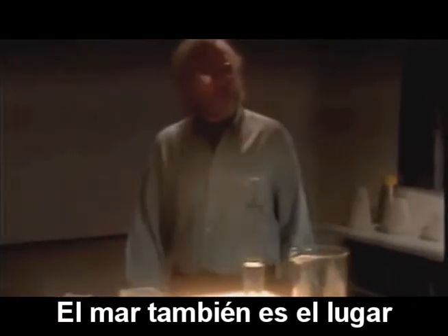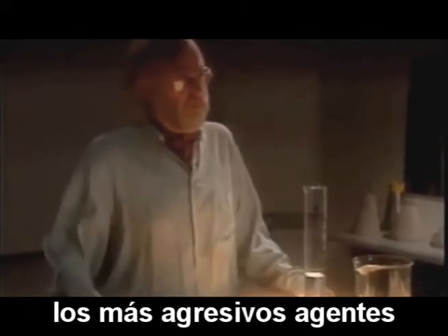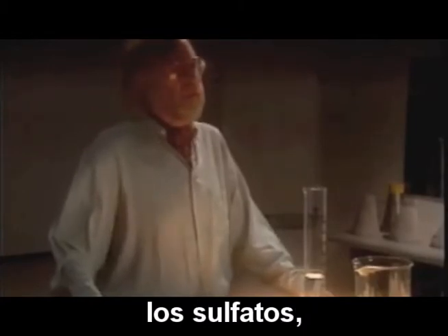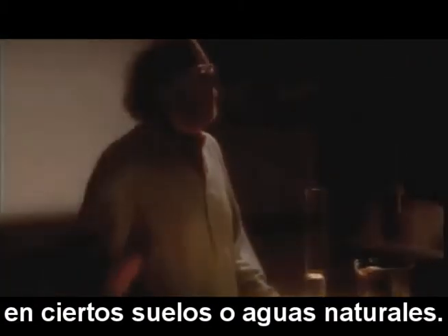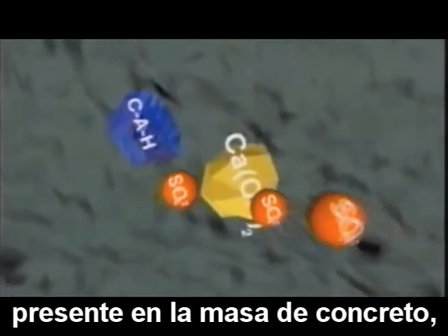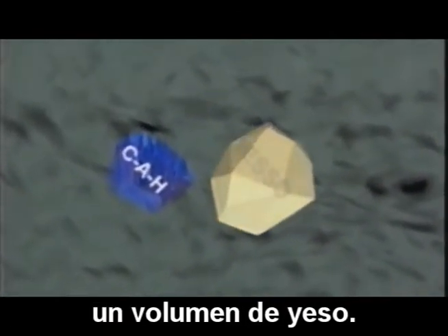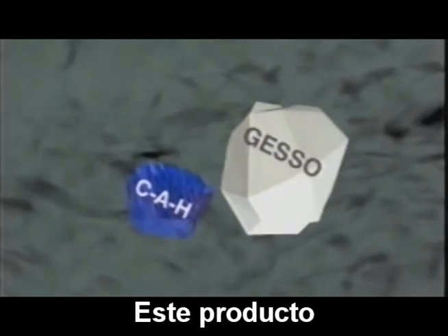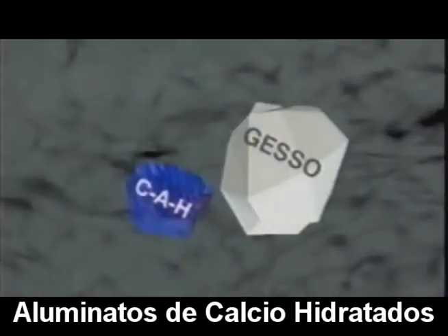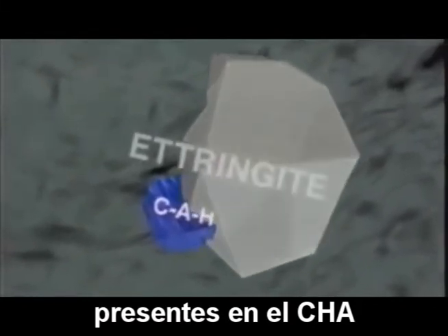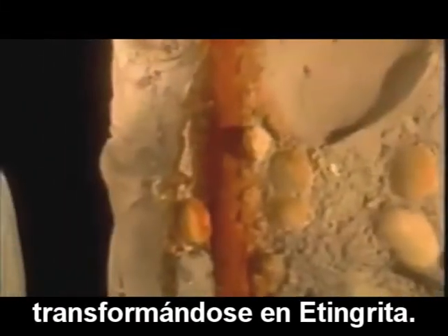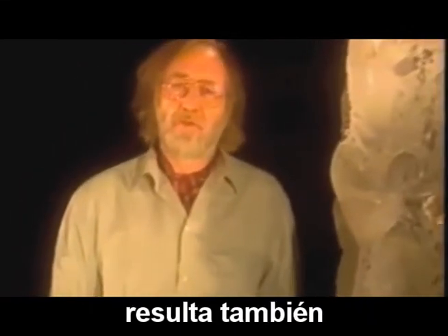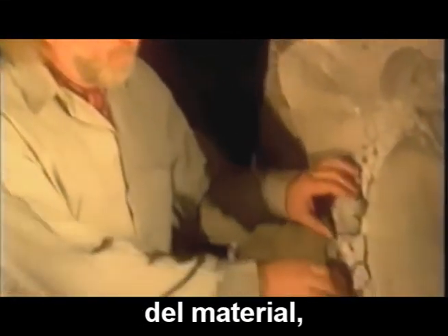The sea is also the place where we find, apart from sodium chloride, the most feared of aggressive agents for concrete, sulfate, which is also to be found in certain soils or natural waters. Sulfate reacts chemically with the calcium hydroxide present in the concrete mass and transforms it into the more voluminous gypsum. This product reacts in its turn with the hydrous calcium aluminates, here shown as C-A-H, transforming it into ettringite. This transformation also results in an increase in volume in the material with a disastrous effect on the structure.